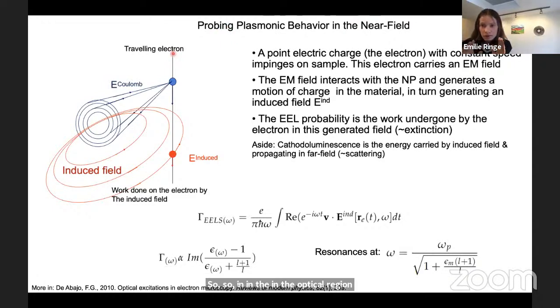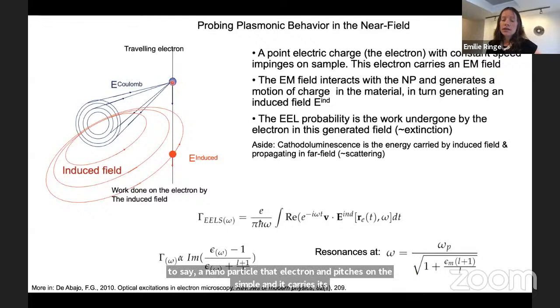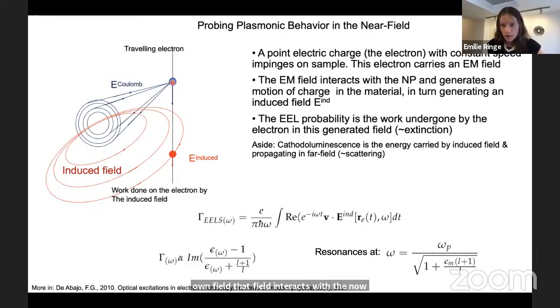In the optical region, when we want to probe localized surface plasmon resonance, what we do is travel an electron onto, say, a nanoparticle. That electron impinges on the sample and carries its own field. That field interacts with the nanoparticle and does that one kick I mentioned a few slides ago. It will polarize that nanoparticle, and that polarization creates an induced field that works back on the electron we are sending back in our column.